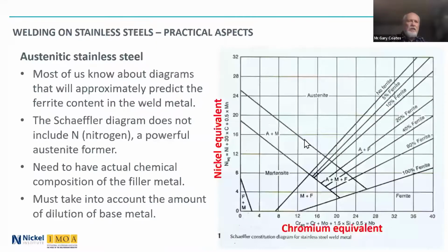Now, most of us are familiar with diagrams that describe the ferrite content of a weld, and they're very useful. They'd only give approximately the ferrite content of the weld. You can't use it to say, okay, we get 8.5% ferrite. That's what I calculated, and expect to actually get 8.5. It could be plus or minus maybe 2% in ferrite for the actual weld. The Schaeffler diagram, which I've shown here, I like the Schaeffler because it shows from between 0 ferrite, no ferrite, and 100% ferrite. It has a lot of advantages in certain areas, but it doesn't show nitrogen.